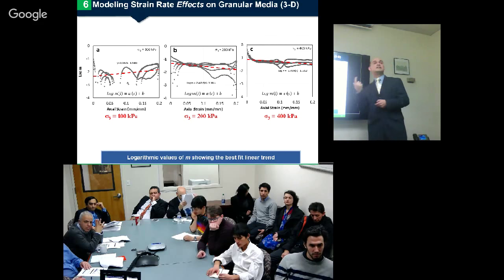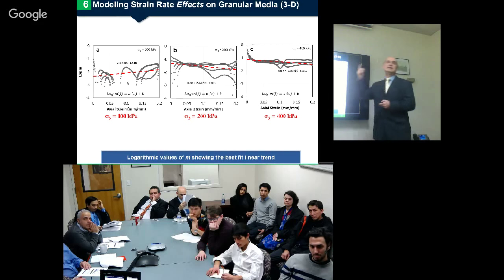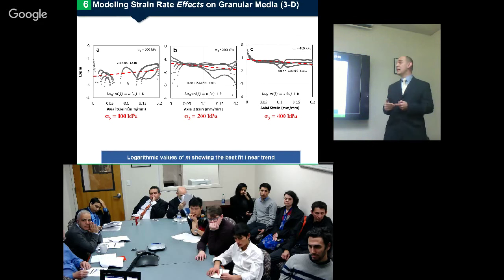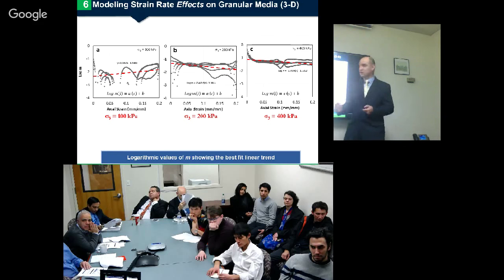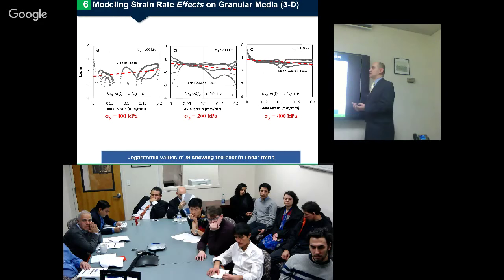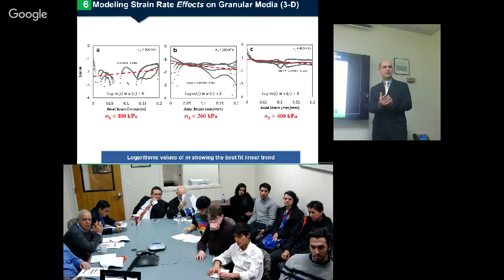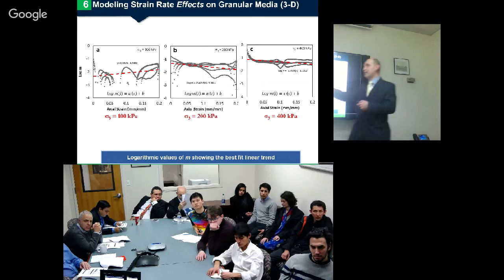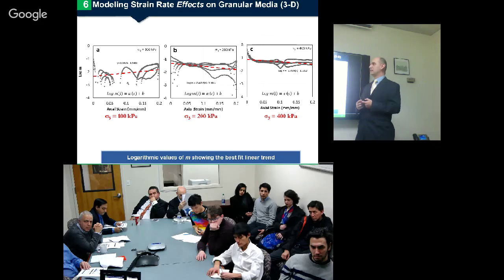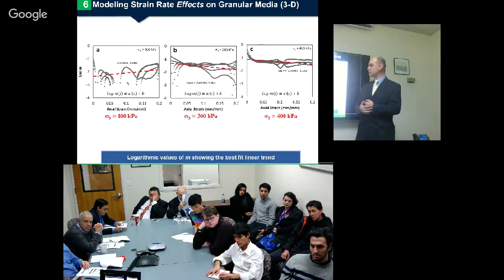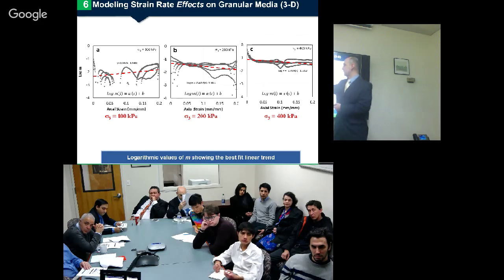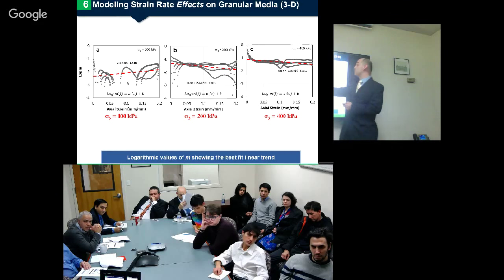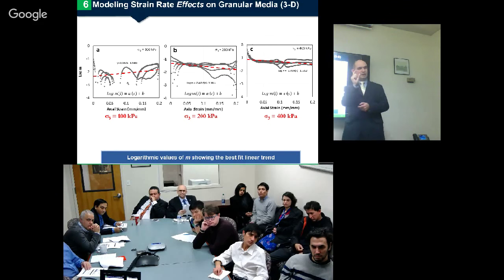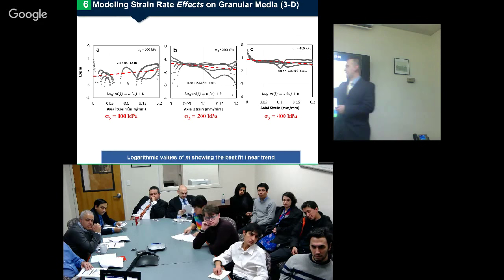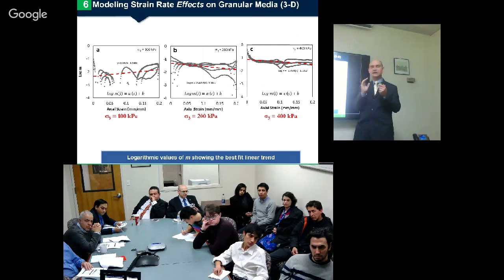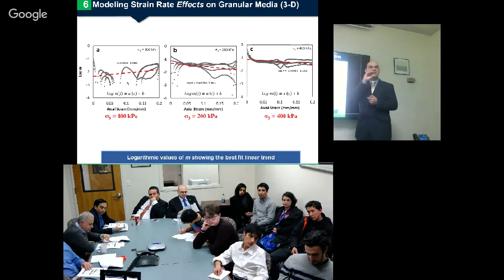Now, for the triaxial compression test, remember we had the previous curves for uniaxial compression. Now for the triaxial compression test, one of the additional variables is sigma 3, the confining stress. So obviously the tests are set to be loaded at different conditions. What we can see here again is this log-log relationship. The log of m versus the axial strain or porosity or void ratio is shown somewhat here. We can see from these three plots, A, B, and C, that at very low confining stress, the dispersion of the results is wide. As the confinement is increased, we can get narrower results.